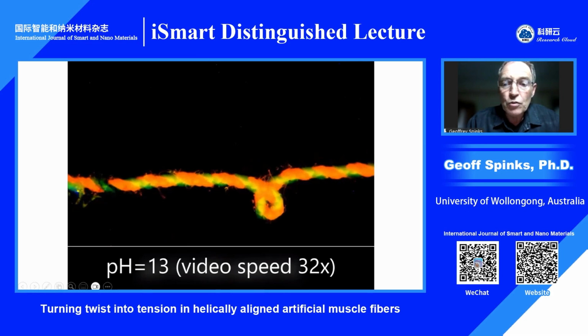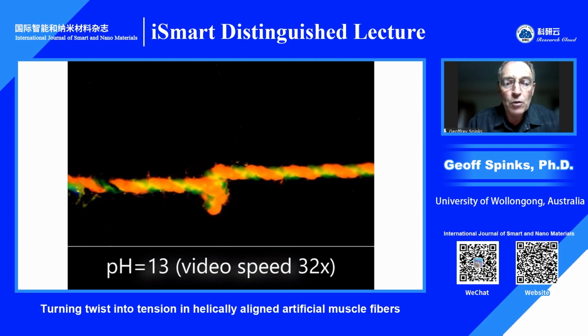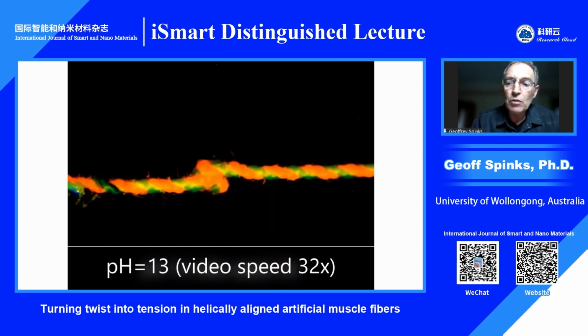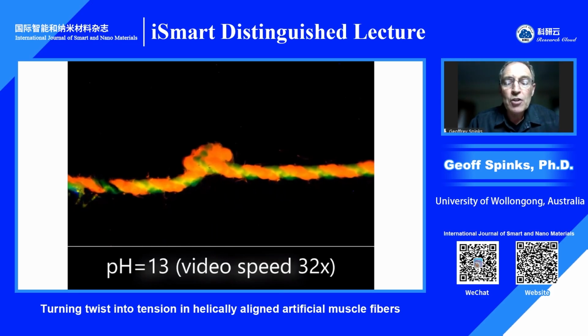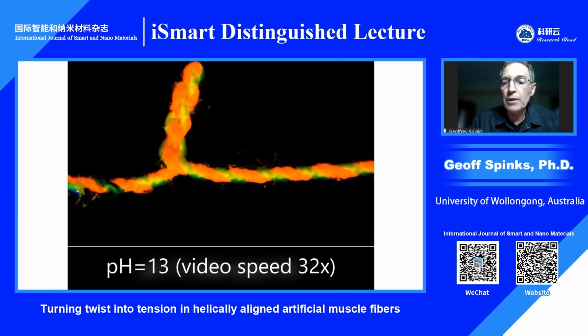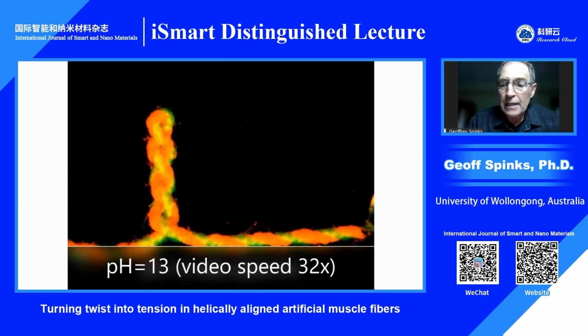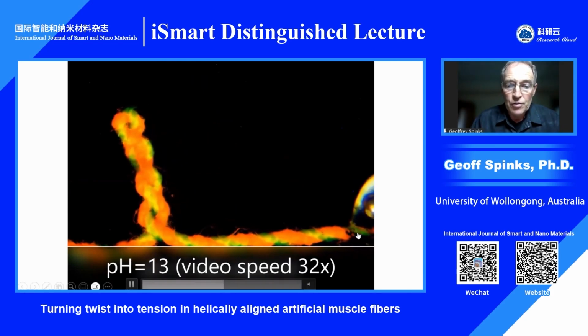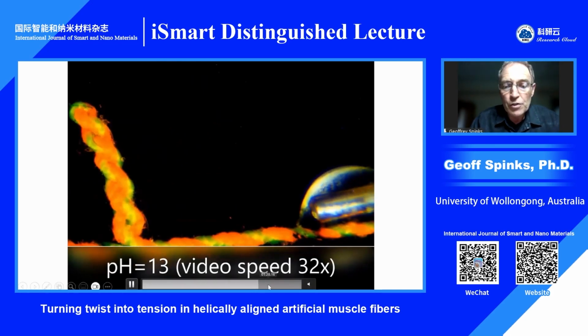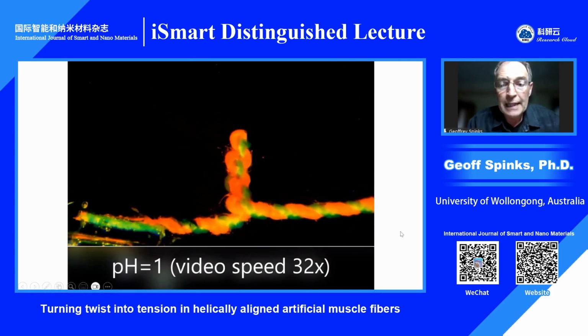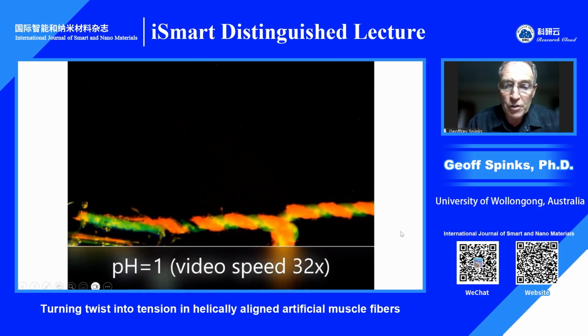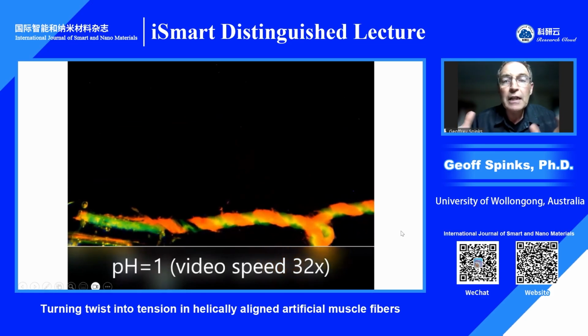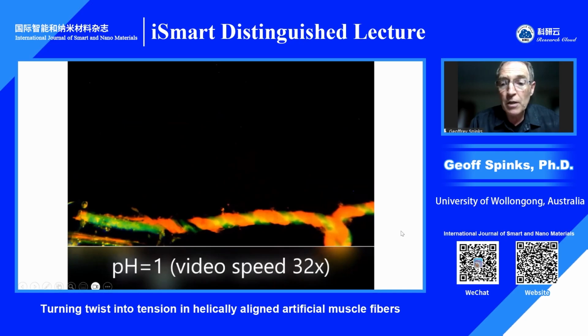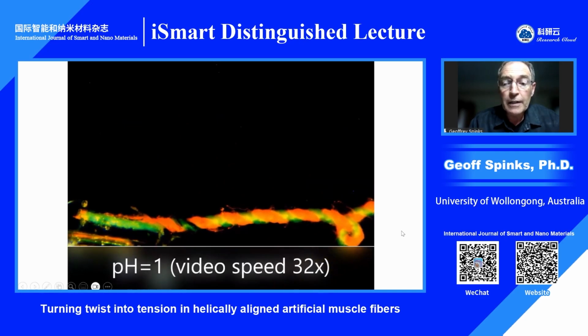It's building up torsional energy, which is relieved by forming these supercoils. And we produce a multi-turn plectoneme type supercoil and a very large contraction in the end-to-end distance of this fiber. You'll see on the right in a moment, the end of the fiber come into screen. And then that can all be reversed by deswelling in the acid and further deswelling by drying in air. So we end up with really large stroke reversible actuation by swelling and deswelling, but amplified by the formation of